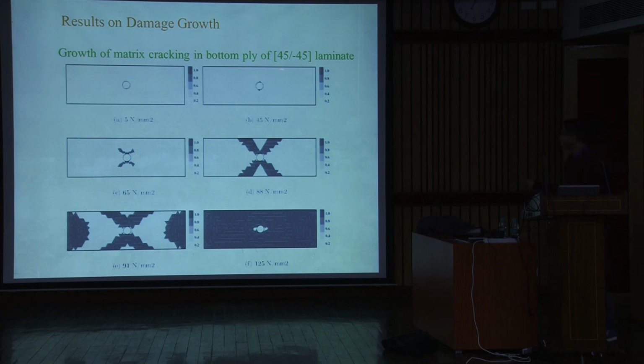As you can see here, you have these plies plus minus 45, and the load is applied off axis. So it is understood that the matrix will fail first, because the fibers are at some angle, they are not oriented along the loading direction. So the matrix is supposed to take more of the load. That is why you see the matrix cracking happening along these preferred orientations.